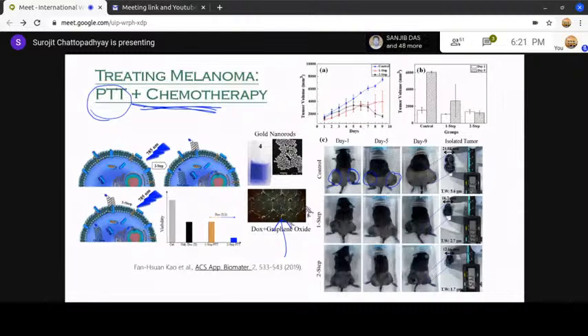For the one-step case, that means look at this panel. For the one-step case, we mix the gold nanorod and the graphene oxide and the doxorubicin and inject into the tumor. I am not targeting it, okay? I am injecting directly into the tumor. And after that, I shine a laser. And I see what is happening to the size of the tumor with time, with the number of days here.